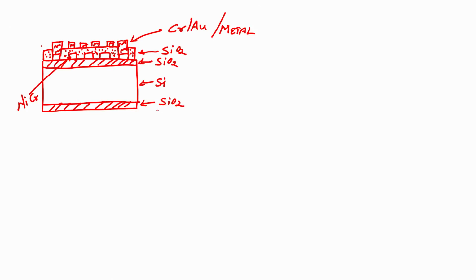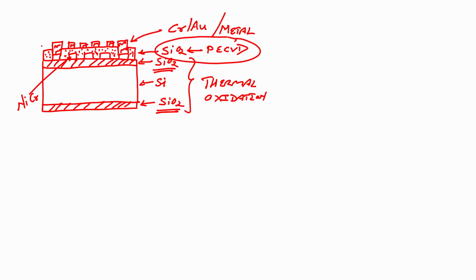All right. Of the silicon dioxide layers, this one and this one are grown using thermal oxidation, while this silicon dioxide is deposited using PECVD. Let me first explain why we have not grown this silicon dioxide using thermal oxidation, like the oxidized silicon dioxide layer where we used thermal oxidation. Why have we used PECVD? Okay. Let me first explain that, and then we will move to the piezoresistive material.